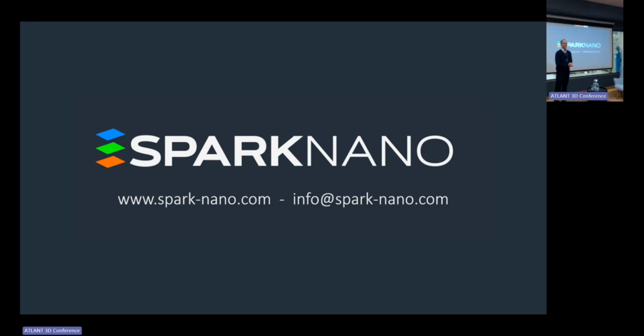Thank you very much. So we have some questions. I have a very unorthodox question. If I understand well, you say the amount of precursor you need scales with the square of the aspect ratio. Yes. Now, is it possible to say, I do the deposition of the metal in 4 times? In this case, I only have to penetrate 1/4 of the distance. In that case, it will take me 1/16 of the time. I have to do it 4 times, but 4 times 1/16 means that the amount of precursor will be 1/4 of what I would need for a single pass.